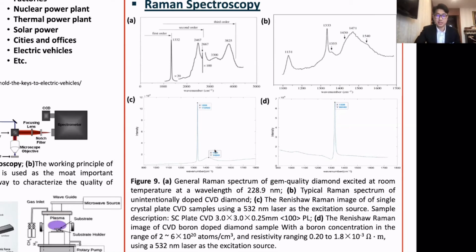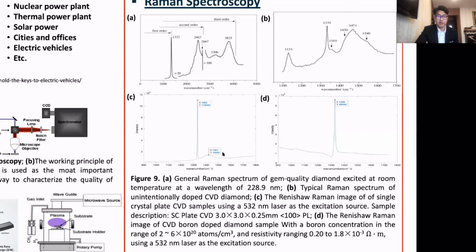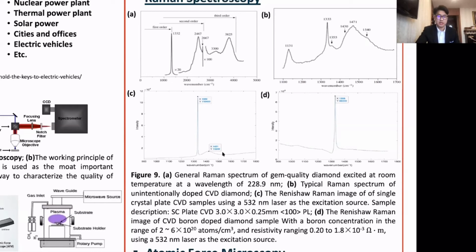In Figure C, we can see that the Raman spectrum is dominated by the first order peak of 1,332 inverse centimeter. And in the typical Raman spectrum, for the peak of 1,421 inverse centimeter, it is likely indicative of a D band, which may exist as a result of polishing damage of sample. In Figure D, it is the spectrum of a boron-doped diamond sample.